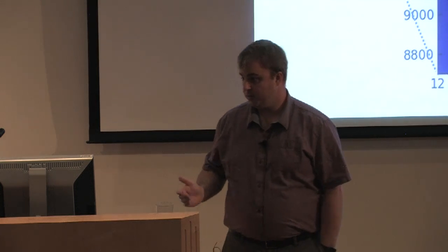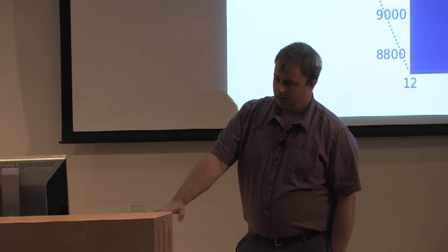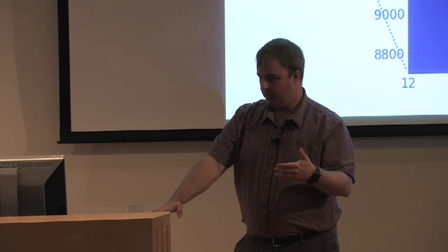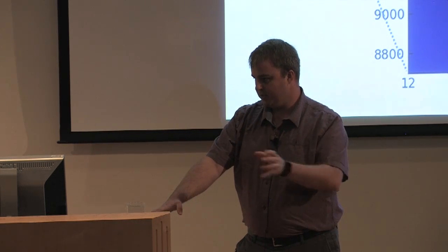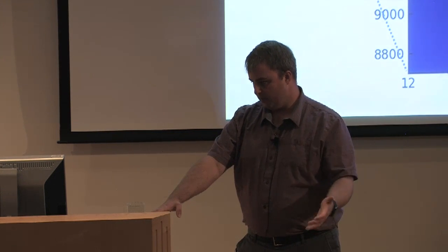But if you can't do either of those things, and there are definitely times when you can't, you can try to characterize the instrument response. The measured peak shape is going to be a convolution of the inherent instrument response, which is basically that footprint, and whatever the inherent peak shape from your sample would be.